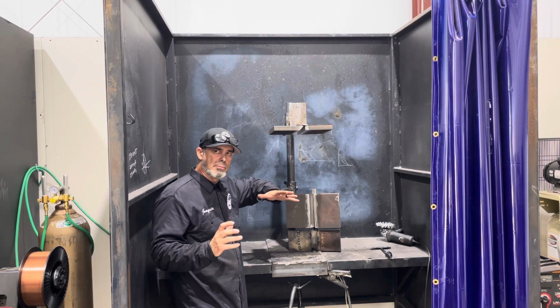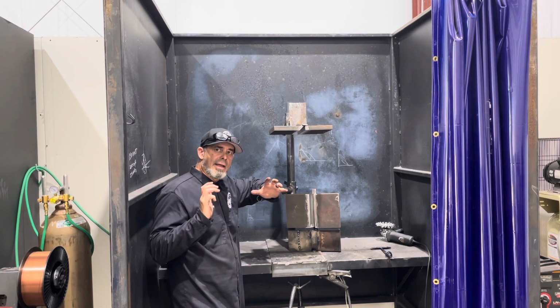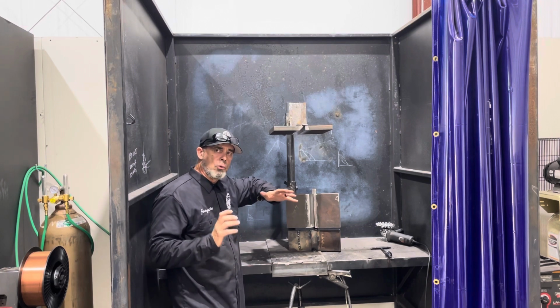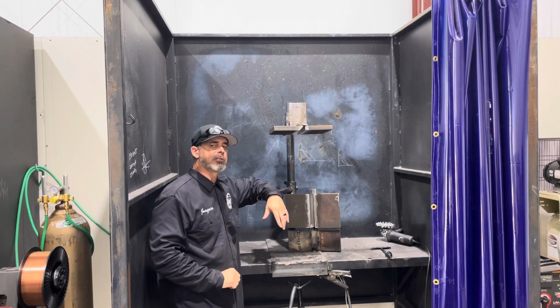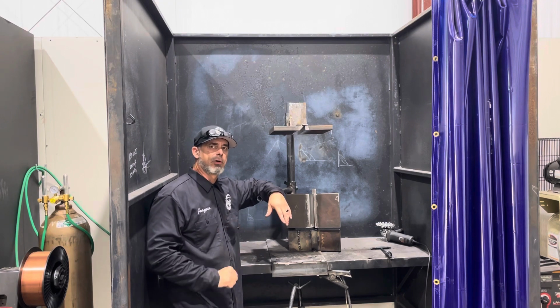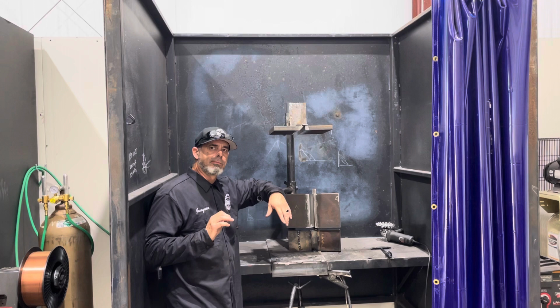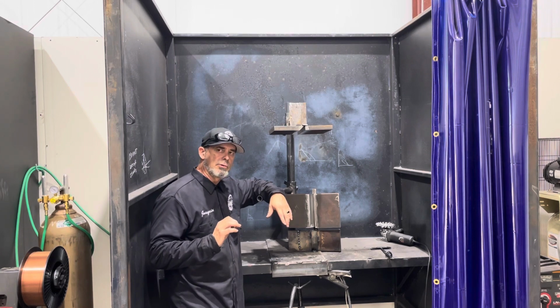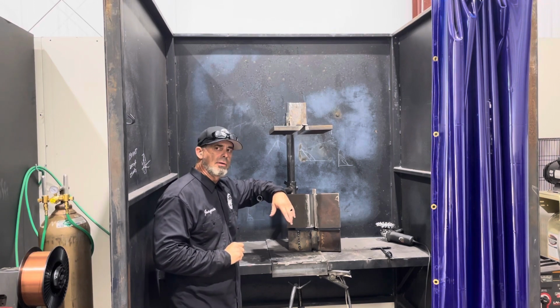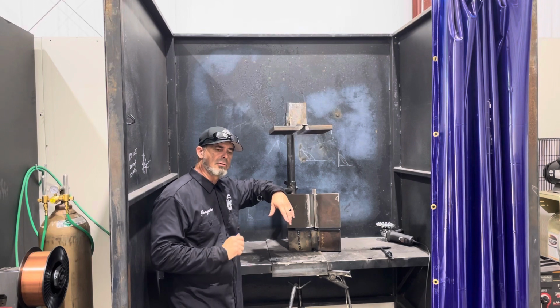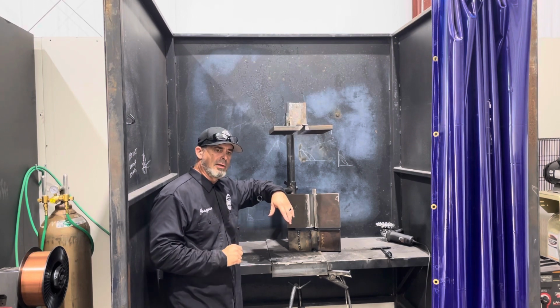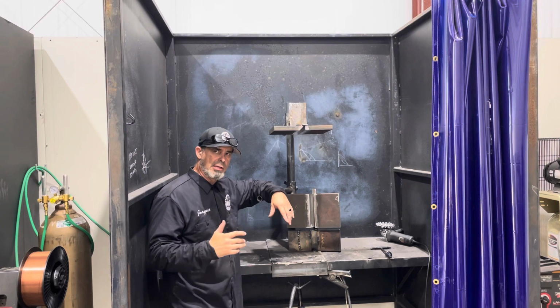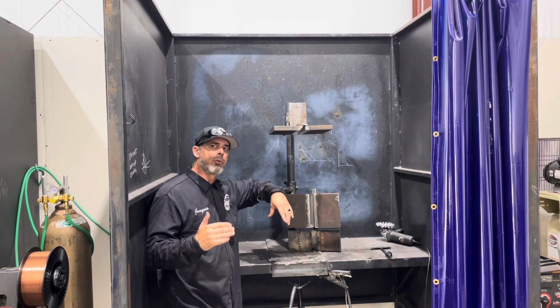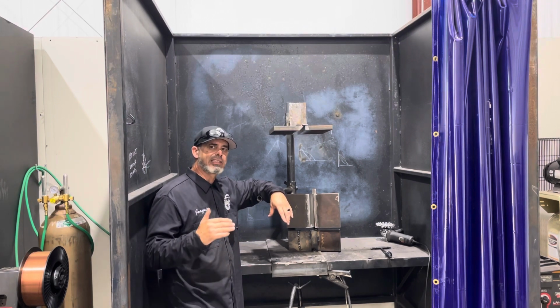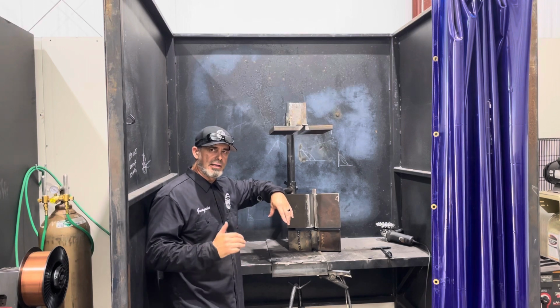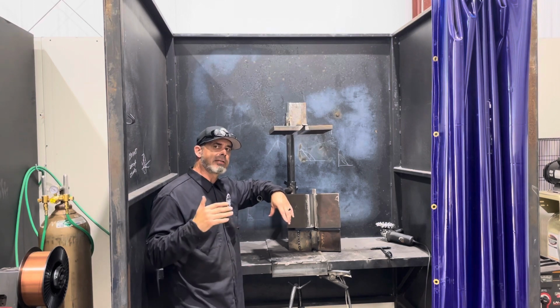This is actually going to be bent, tension tested, and certified at a point that this welding procedure is a proven, solidified welding procedure. Preheat is going to be very important with this procedure. So the WPS for this says 250 minimum is the preheat. We'll take it up to 300 on our preheat. Interpass temperature, according to D1.1, for 514 is not to exceed 400 degrees. Again, 400 degrees is interpass temperature.